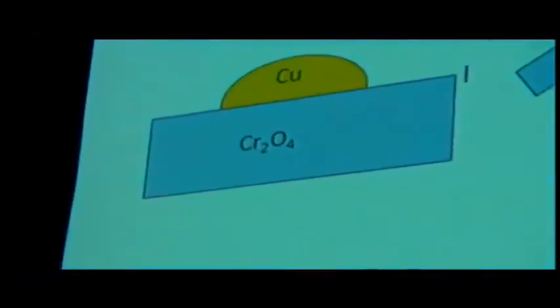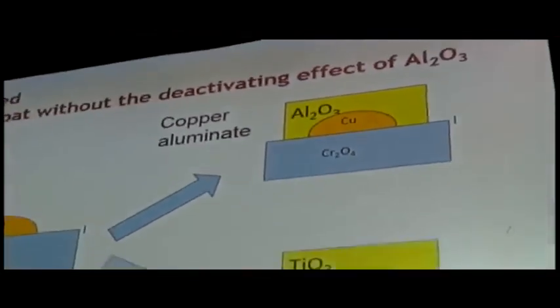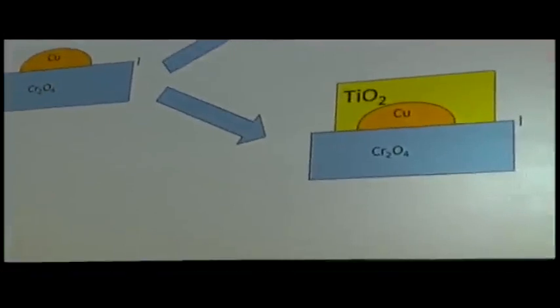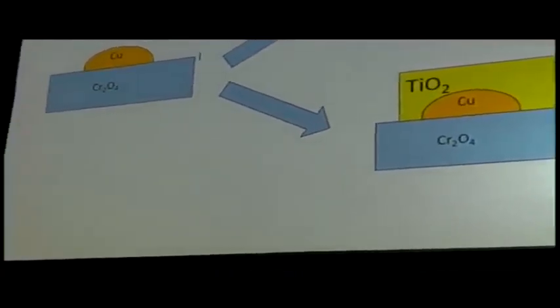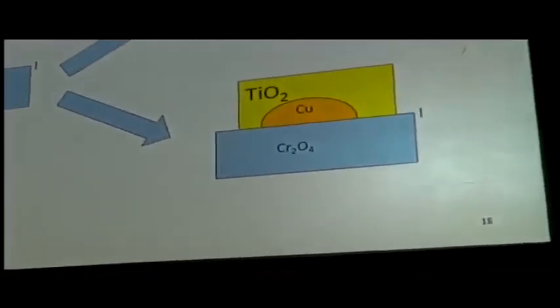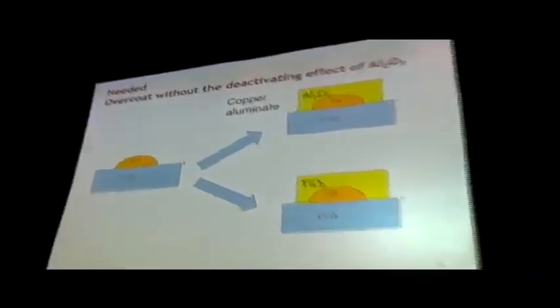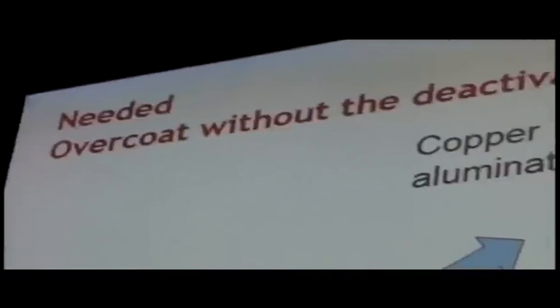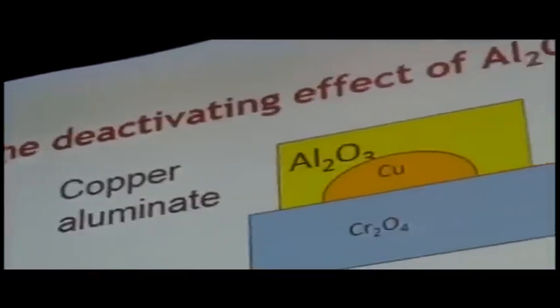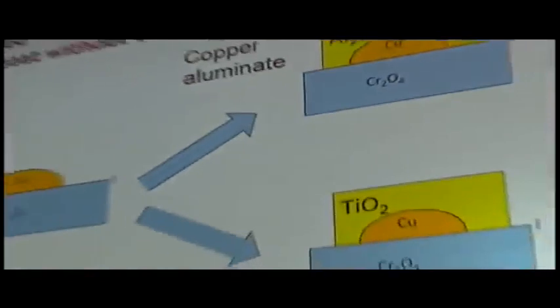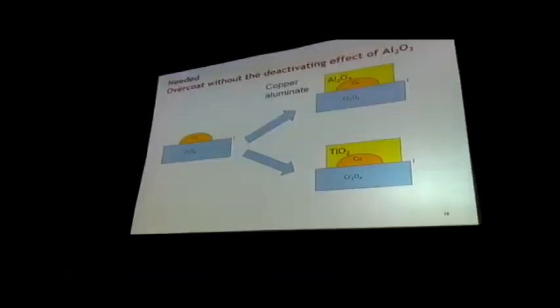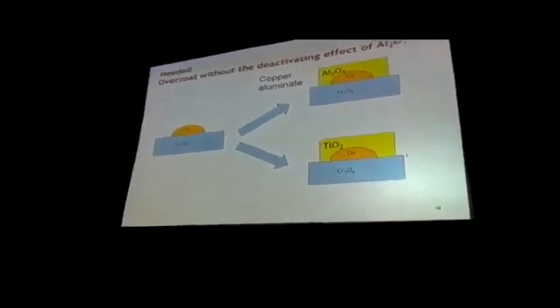So when we put aluminum over the top of the copper, we form this copper aluminate phase, which is less active than the copper by itself. What I'm going to be showing you here is we can replace the alumina overcoating with titania, and the copper does not form as strong a titanate on the surface here, which basically can form that cage over the material without changing the chemical nature of the copper. That is interesting.